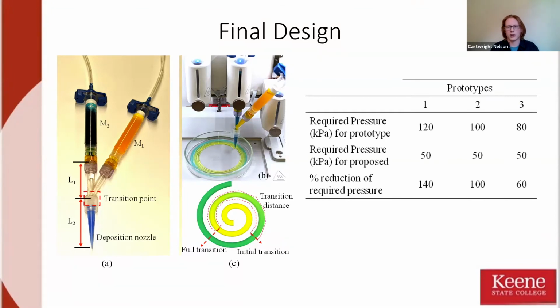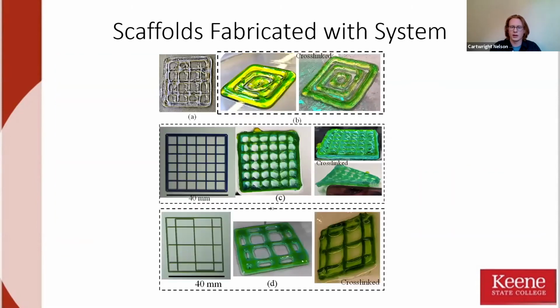The prototypes I showed before, the first one required 120 kilopascals of pressure, the second 100, and the third 80. And then the proposed one here only requires 50 for that print, but if it was a less viscous material, it would require even less. So this is a significant reduction in required pressure, which is very good for cell viability and proliferation, because you wouldn't want to kill all the cells while you're printing them, because then your scaffold would be useless. And one of the ways we reduce this pressure is with the shear thinning properties that Slesha mentioned.